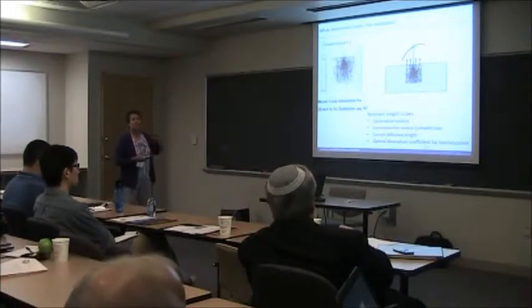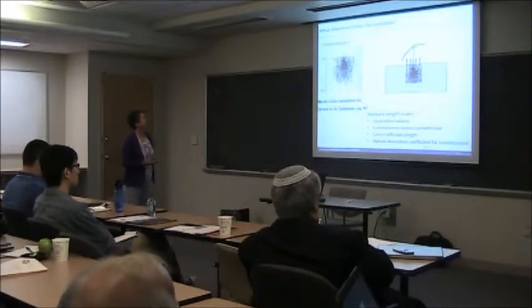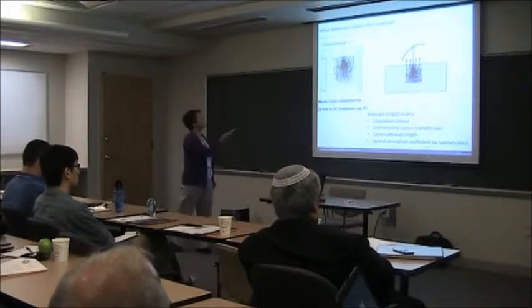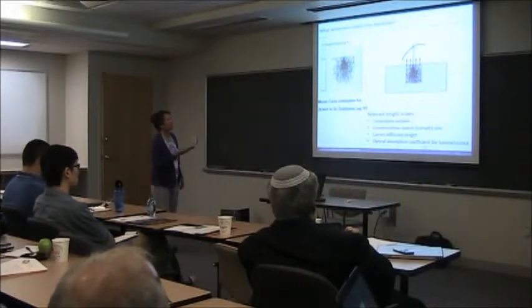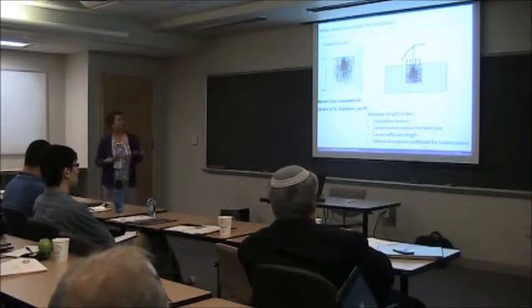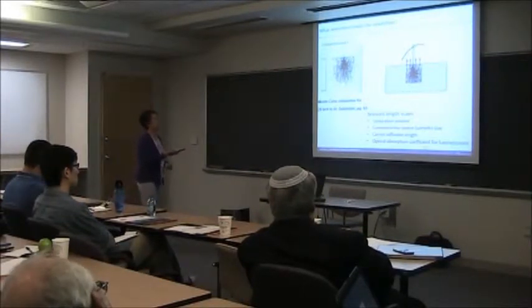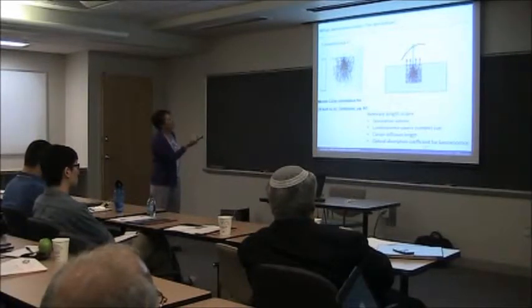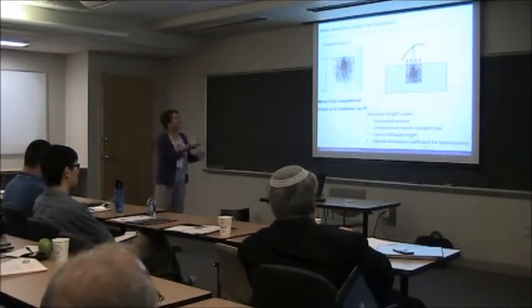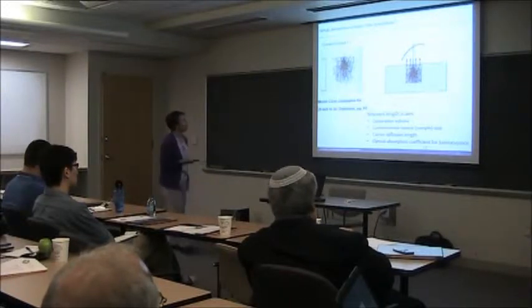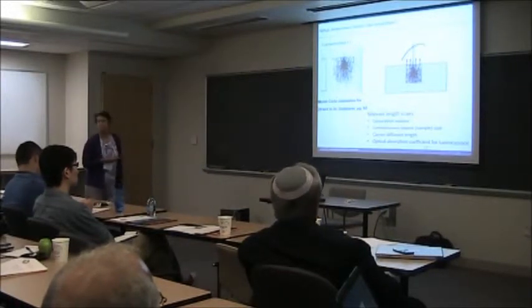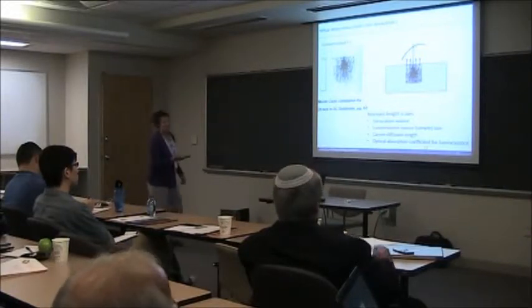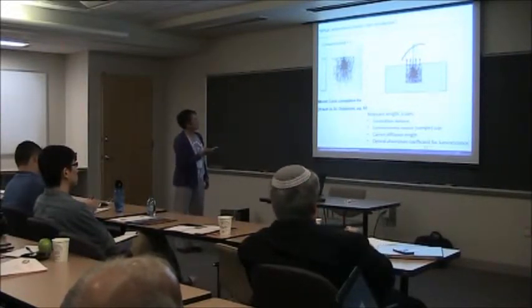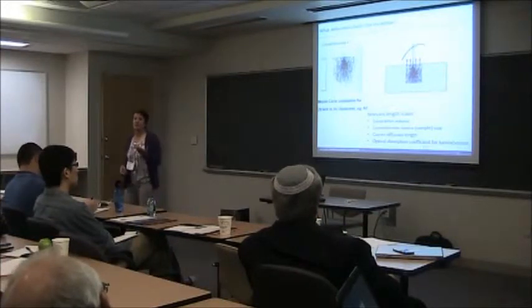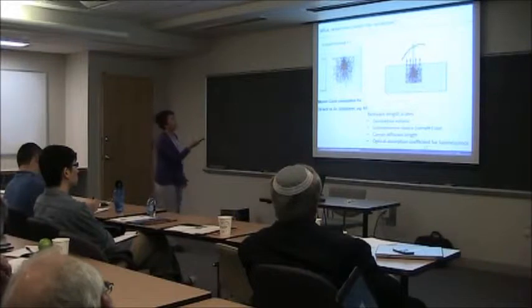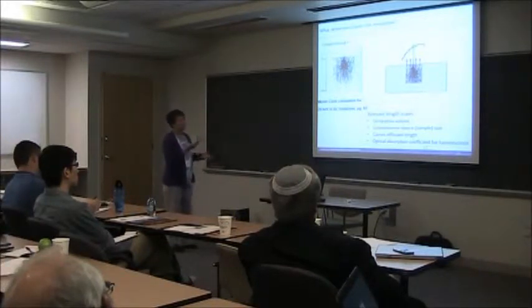The original driver was to get better resolution from your cathodoluminescence. Everybody who does CL knows that an electron beam coming in creates a generation volume. The size of that volume depends strongly on the excitation energy. So here's 20 keV in silicon. You can see that no matter how tiny that little guy is, you excite secondary electrons and everything that follows, in this case over a range of a few microns. Now the trend since this early work is that people are now doing 5, 3, even 1 keV. And with all the improved optics, that generation volume can go very small, but you lose signal too.